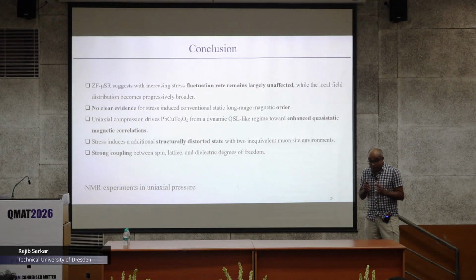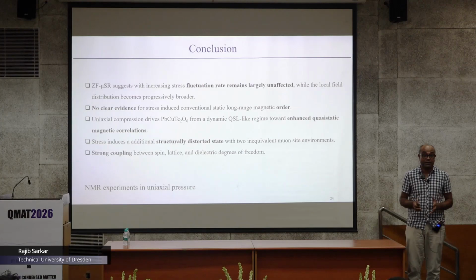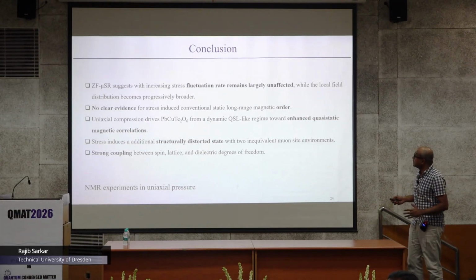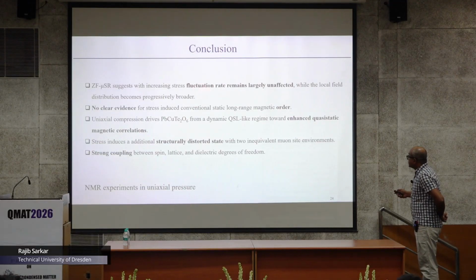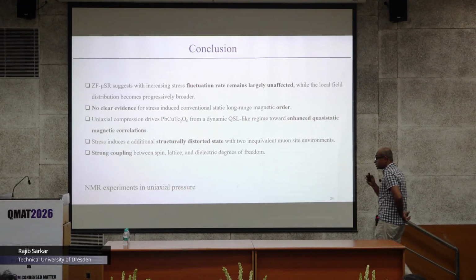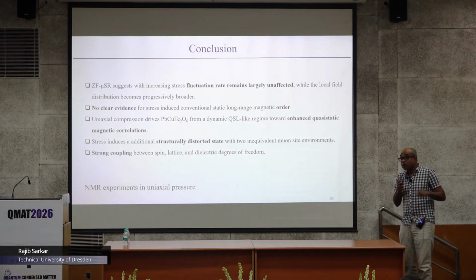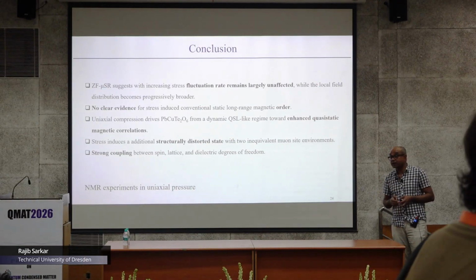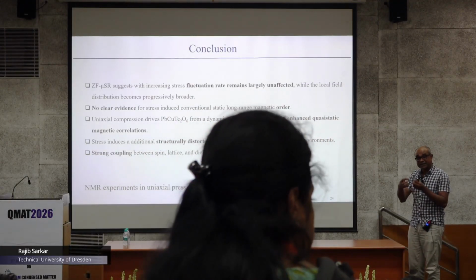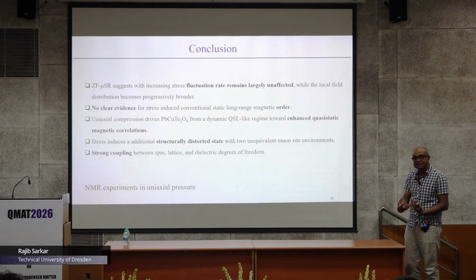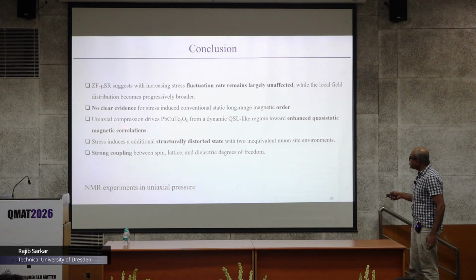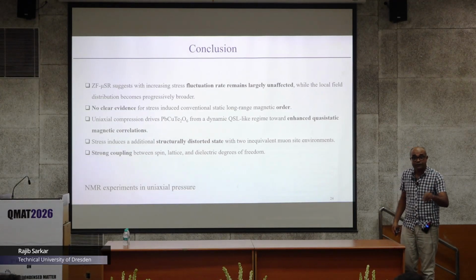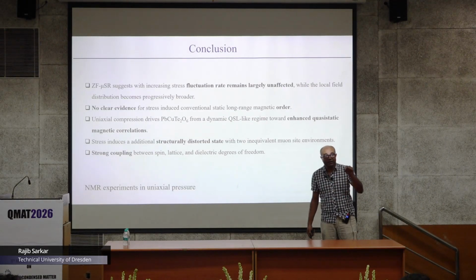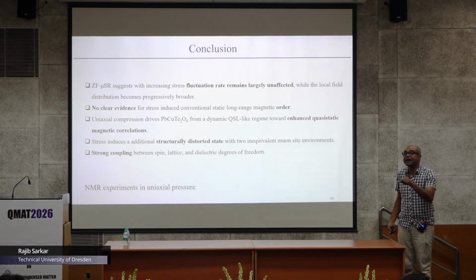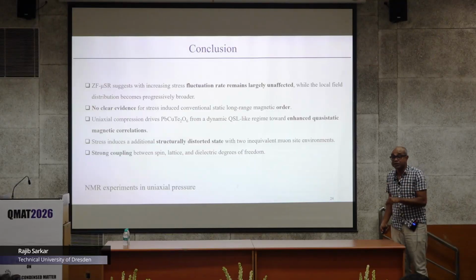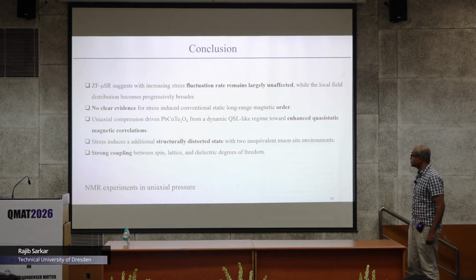So what information do you get from all this data? The take-home message is very clear. First, we have a largely unaffected fluctuation rate because of the slow fluctuation, but our local field distribution, coming from the electron spins, is progressively broader. That means static or quasi-static correlations are developing, but we cannot give conclusive evidence of long-range ordering. If there were long-range ordering, you would have seen at zero field a well-defined static order, a well-defined oscillation or strong damping. That is not there, so we cannot tell.